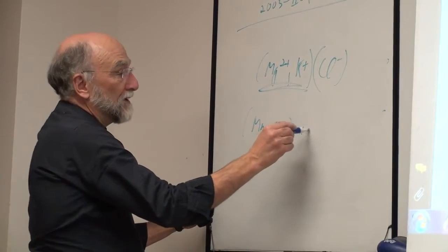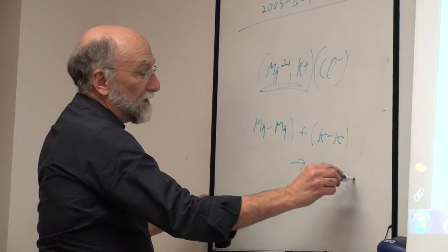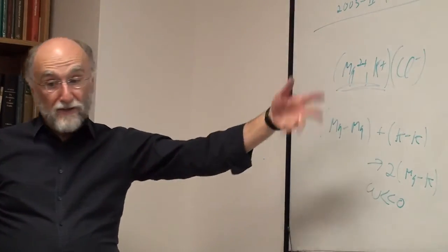Between the magnesium and potassium on their own sublattice, you would have a very strong tendency for magnesium and potassium to be second nearest neighbors. You would have a very negative short-range ordering parameter. You treat it on the sublattice. So this is your mixing sublattice. You can ignore the chlorine sublattice, and you treat it by a simple one sublattice quasi-chemical model with a large degree of short-range ordering. So the tendency is for magnesium to have potassium in the second coordination shell, and vice versa.